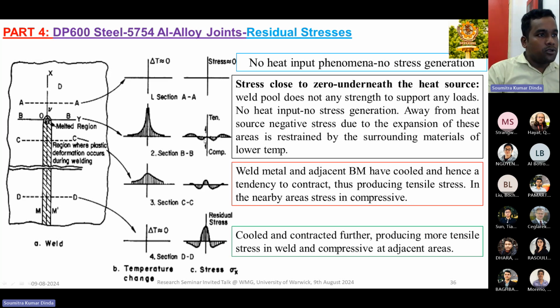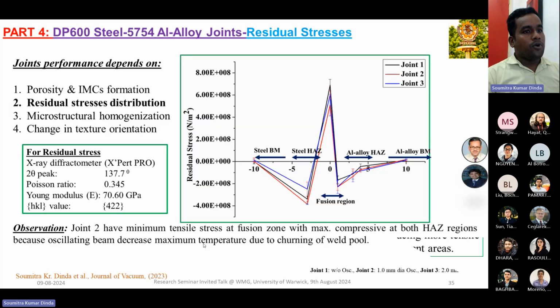But what will be the stress value? The closest one will be the negative one, and that will be balanced by the positive stress of the surrounding material, which is at a lower temperature compared to the region adjacent to the welding. Suppose our condition is C, where we are just crossing the heat source point. Then the peak temperature will decrease, and the weld metal and the adjacent base material go for cooling, so contraction will take place, liquid to solidification, producing tensile stress, and this tensile stress will be accommodated by adjacent compressive stress. When we finish our welding, there will be no temperature difference, but our residual stress graph looks like this. This type of graph we also got from our study.